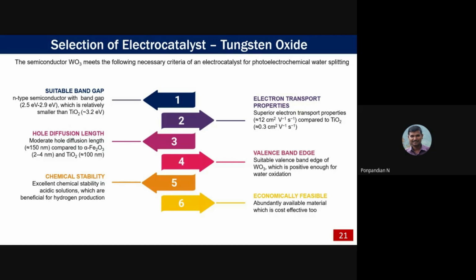There are two ways. One, in the bulk you can dope other foreign elements. In that way you can change the band gap. But in the nanomaterial, when you can reduce the grain size to nanometer scale, or even less than 50 or 10 or 5 nanometer, you can easily tune the band gap of this particular semiconductor. That is the first way. You have to get the clear band gap for this particular application.